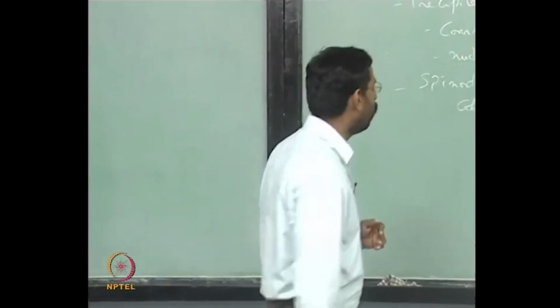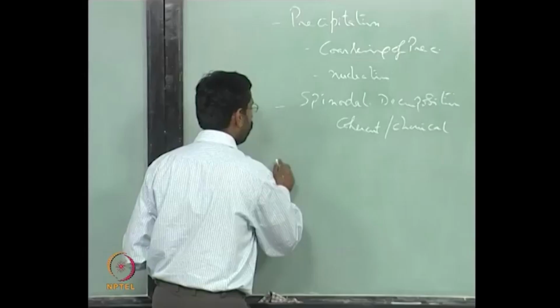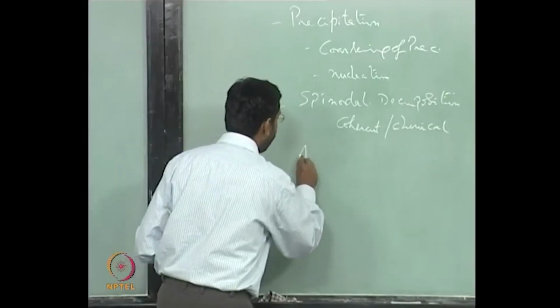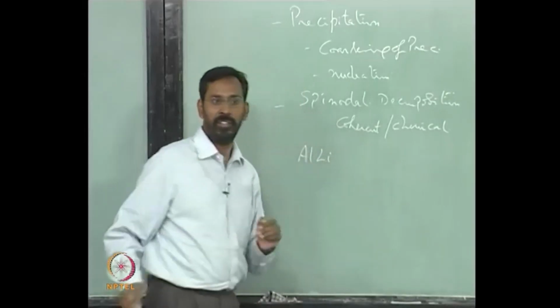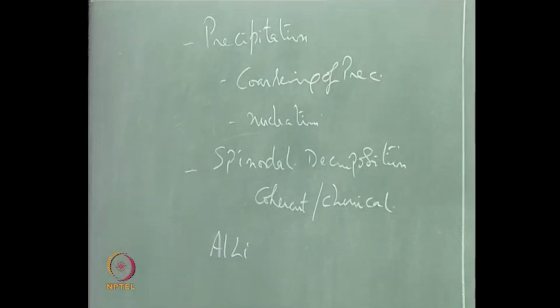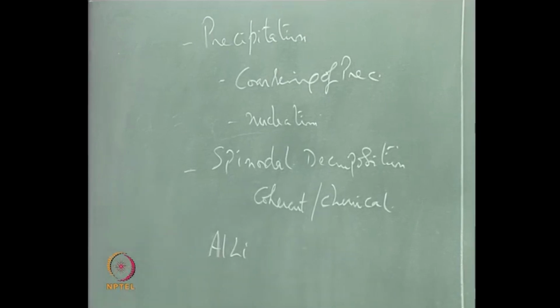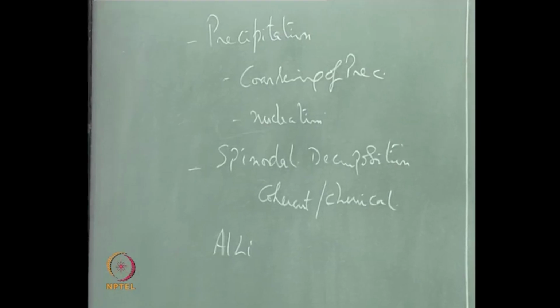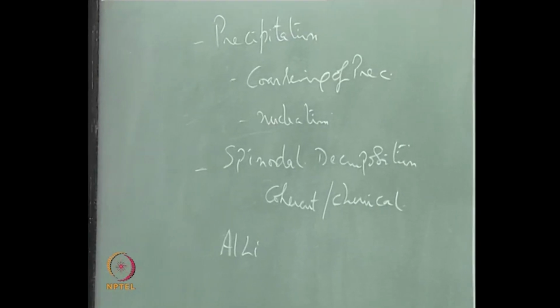But also, if you look at the aluminum lithium phase diagram, you see a phase called AlLi, the stable phase in the aluminum lithium diagram. In fact, a large number of people have worked on aluminum lithium in aerospace industries to see if they can have a replacement for aluminum copper alloys, so that you can have much lighter alloys. But there are problems. The first problem is that lithium, being the lightest metal, has a very small atomic size. First and foremost, lithium is reactive.